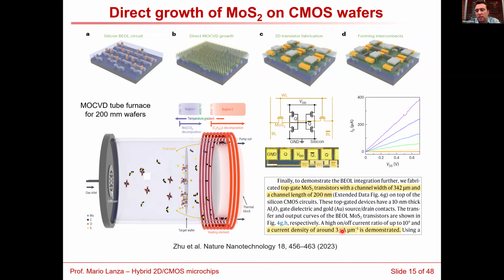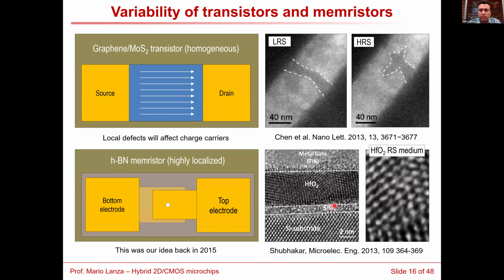And in fact, the current density is 10,000 times lower than the state of the art for molybdenum disulfide transistors. So basically, it's a nice proof of concept, but there are a lot of improvements to do in this method. And actually, because this temperature is 550, I'm also a little bit skeptical to see how they can reach the target mobilities required by the roadmaps. So anyway, it's an interesting approach that I wanted to mention.